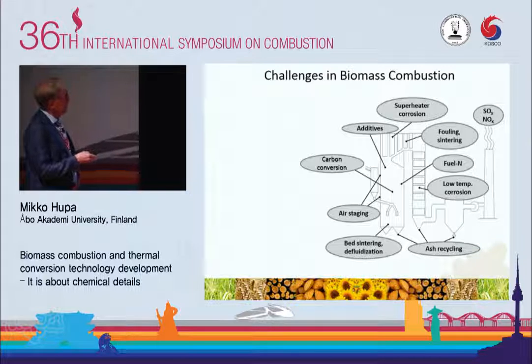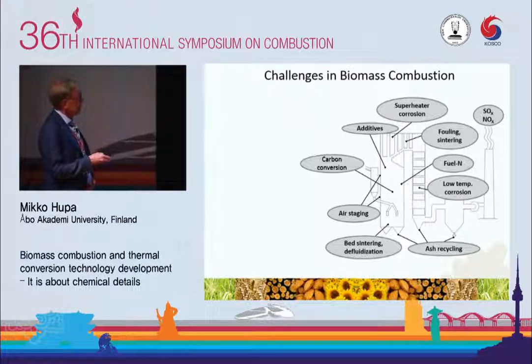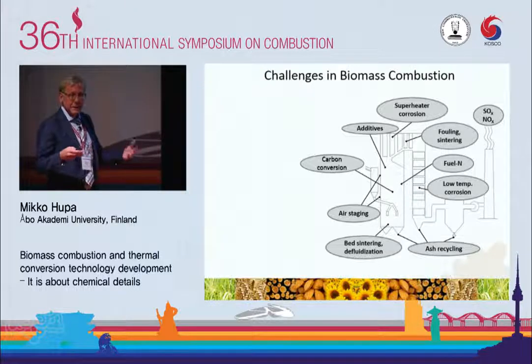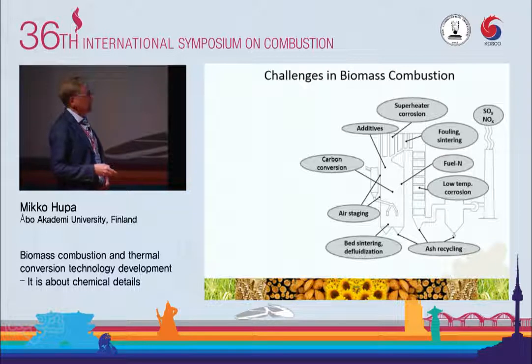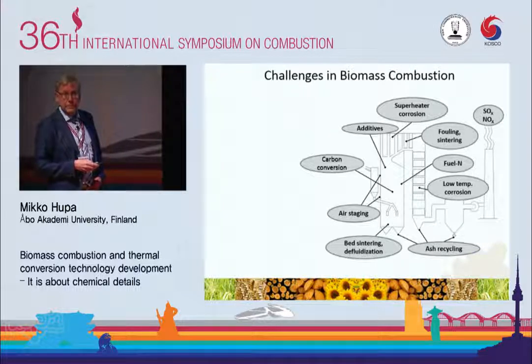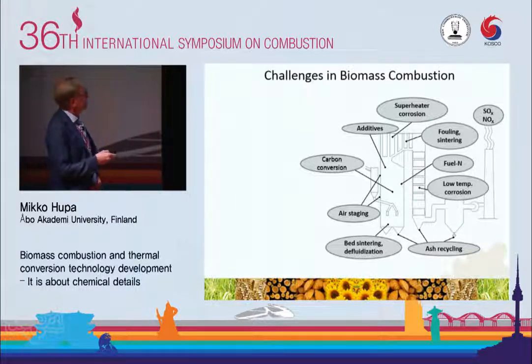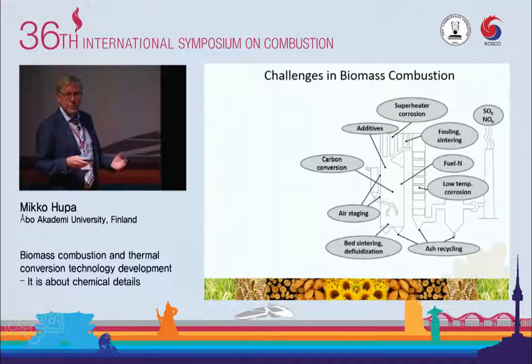Fluidized bed, very special feature is the bed sintering. Fluidized sand bed is sensitive. If it starts changing composition, it may start forming larger particles, and it may defluidize. Very, very difficult and common problem when using biomasses. Nitrogen oxide chemistry requires good knowledge of air staging or vice versa. Carbon conversion, something about fuel reactivity.